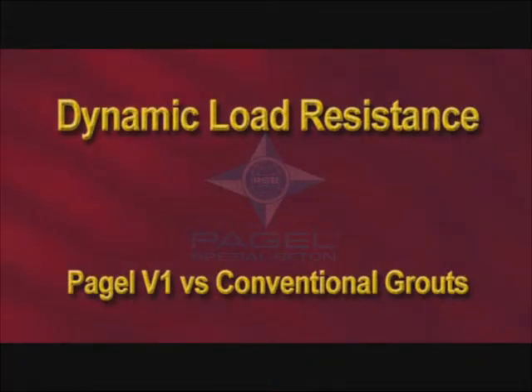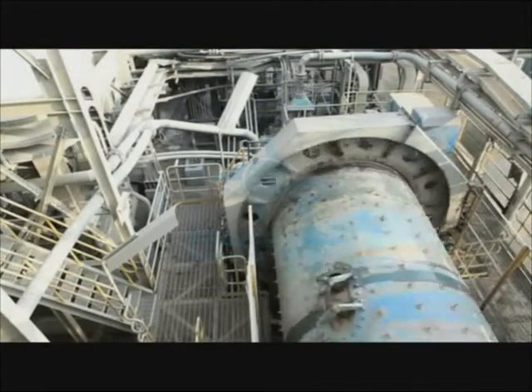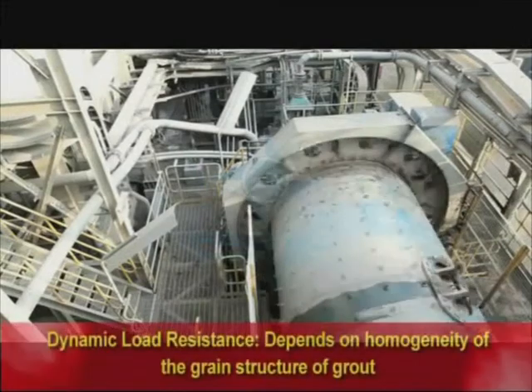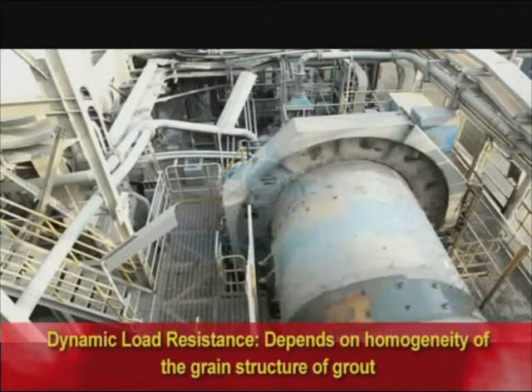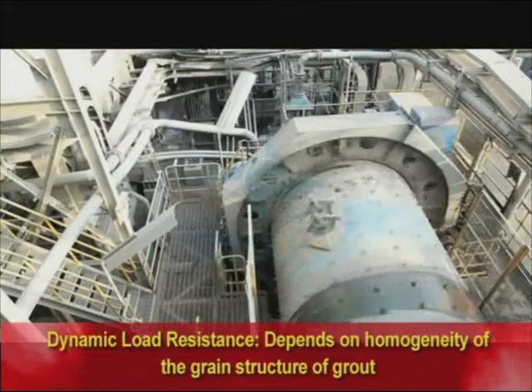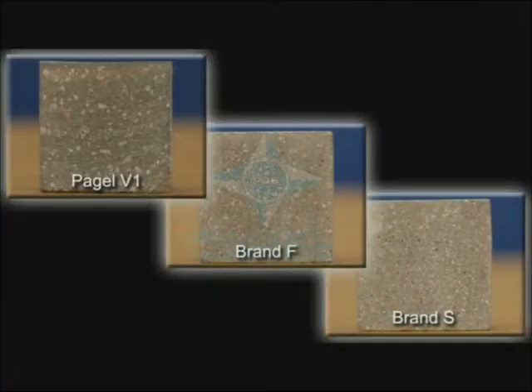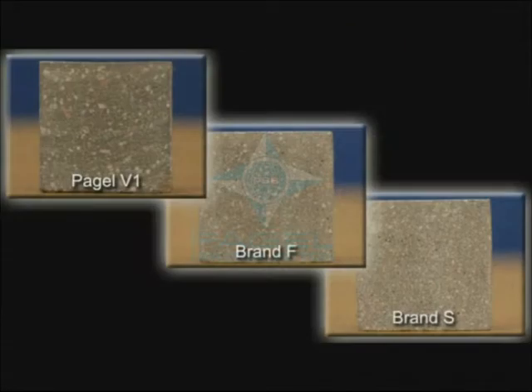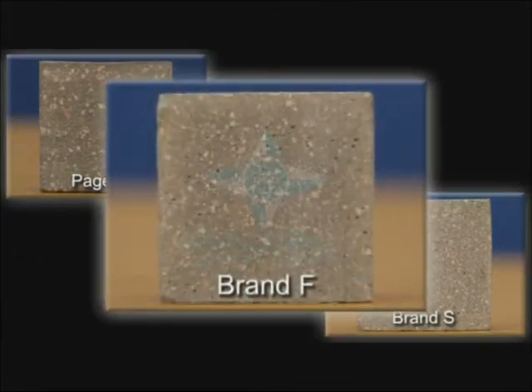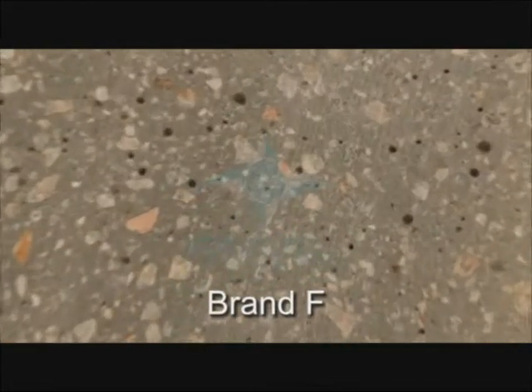Dynamic load resistance is the ability of the grout to handle loads that are constantly varying, as in the ball mill of a cement plant. It is a function of the evenness and homogeneity of the grain structure of the cured grout. As we see from the cut sections of these blocks, the grout of brand S is inferior with very small grains and formation of many holes and voids. Brand F also has small grain size and several holes.